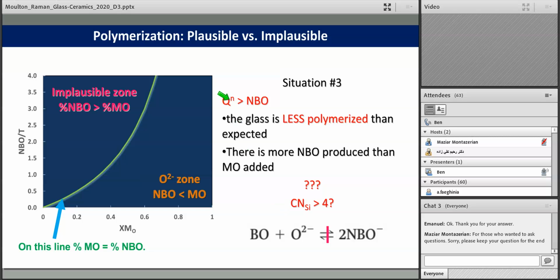The final situation: if we count up the non-bridging oxygen, our QN, and determine it from another method, we could have more non-bridging oxygen per tetrahedron than metal oxide added. In this case, we'd be in this field up here. This is termed the implausible, or some people would say the impossible, zone. The melt is ultimately less polymerized because there's more non-bridging oxygen than expected from the amount of metal oxide added. This is only possible in the rare situation where the coordination changes and the amount of tetrahedra, the amount of silicon, is not constant. So this reaction is not the only thing that's happening, and you need to consider other alternatives.